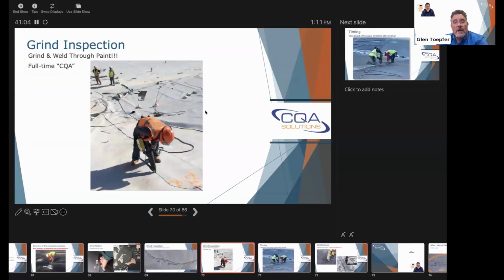Grinding through dirt, paint, things like that. This is one that I use in some of our training. You can see I don't have the photo where it was finished welded here, I guess, but they abraded through the paint, so they got the paint all over the place and scattered with the grinding disc, and then they welded through it. Under full-time CQA, we were doing an audit. Well, here's your two CQA people. They're down at the toe of the slope. They're not paying any attention to what's going on there. You need to be up and seeing things firsthand so you can catch these problems and deal with the problems.